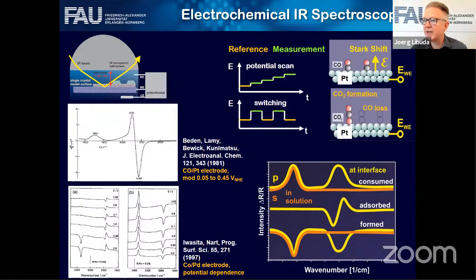All these spectra that you see here are difference spectra. There's no way of taking an infrared spectrum at an interface without doing it in the form of a difference spectrum. So it's always difference spectra. What you do is you have a program via which you change your potential, for instance in the form of such a staircase, or you go zigzag, and then you take one potential as a reference and the other potential as your measurement. And then you take the difference between these two potentials.